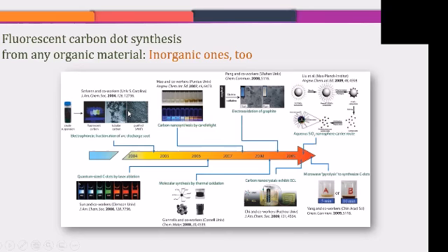But in 2004, carbon nanodots were found by mistake. They were trying to make purified single wall nanotubes, and they found that one fraction of the whole product was fluorescent. When they investigated, they found that carbon dots are carbon-based nanomaterials with an amorphous, zero dimensional or spherical structure, and they might be single layer or multiple layers, and they are fluorescent in some way.